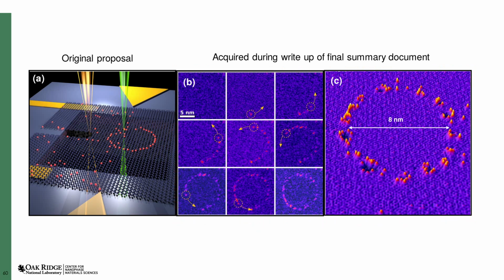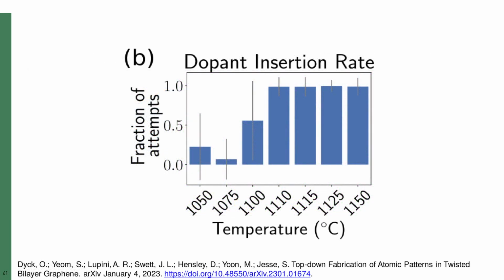This was a fantastic breakthrough, and the next obvious question is, what happens if we vary the temperature? We performed these experiments at a bunch of different temperatures, and what you're looking at here is a bar plot summary of every outcome as a function of temperature. A hole is represented as a 0, a dopant is represented as a 1, and for each temperature, the bar height represents the average result.